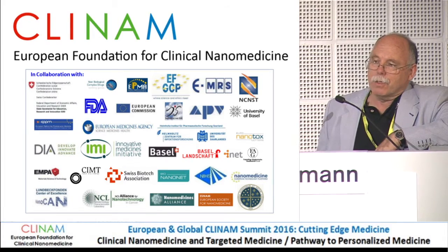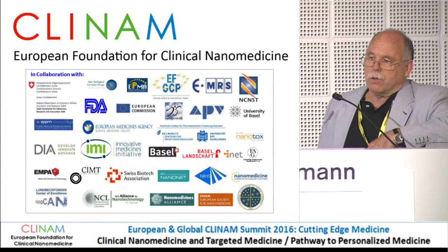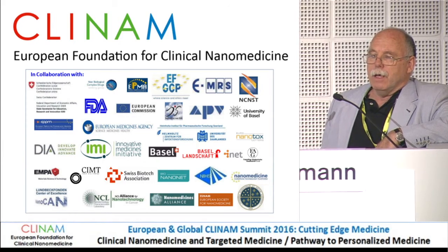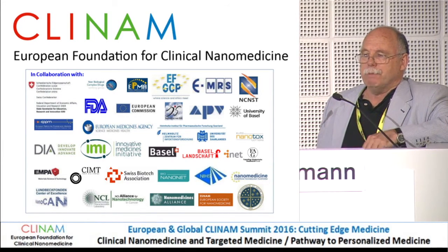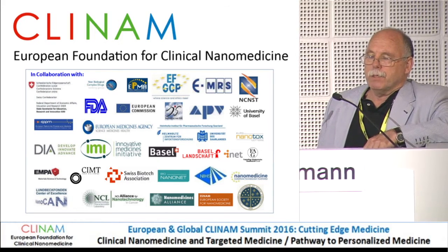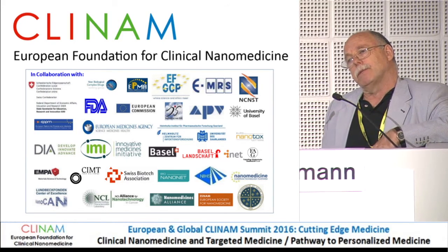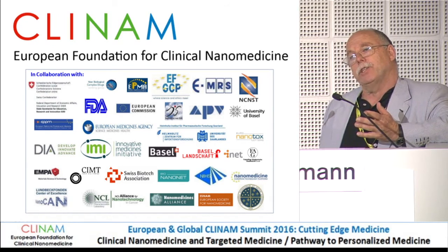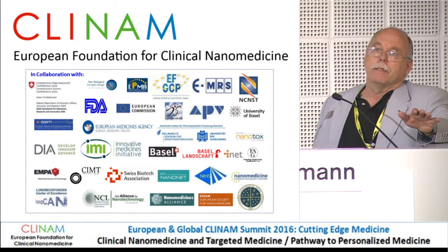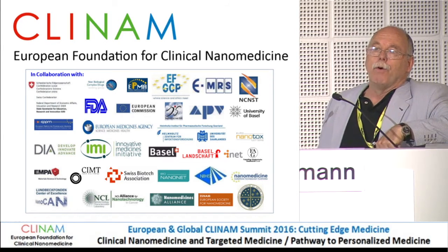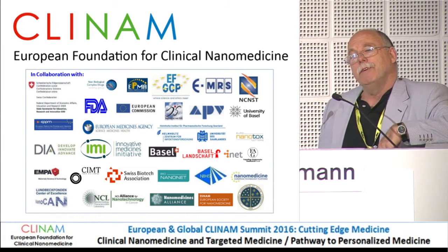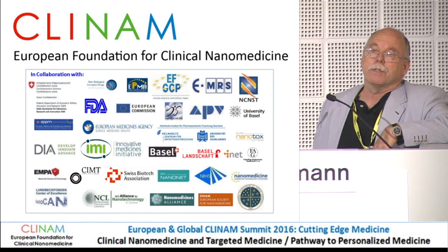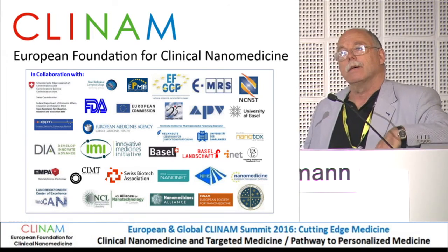What we have also observed in vivo with ROS and maybe other immunotoxicity is that after injection in big animals, sheep for example, between 24 hours and 72 hours, we have a slight inflammation, a little bit of fever, but then this disappears. I think this is acceptable for a treatment. Whether it is acceptable for diagnosis, we have to discuss. But still, we are on the good side.